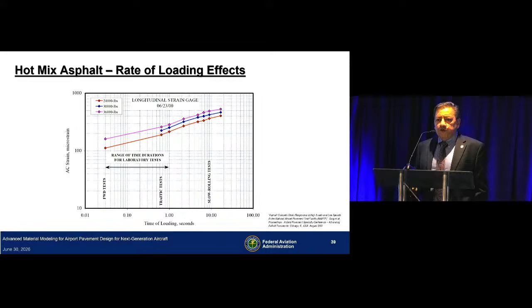Effect of rate of loading. Asphalt concrete is a viscoelastic material, so rate of loading has a big impact on how it performs. What you see in this chart is asphalt concrete strain, the strains at the bottom of the asphalt layer, and time of loading in seconds. So we started testing at NAPTF what we called slow rolling response tests, where we were testing at speeds of 0.25 feet per second. So it's basically very slow speed. And at that speed, you're basically measuring viscous flow of the material.